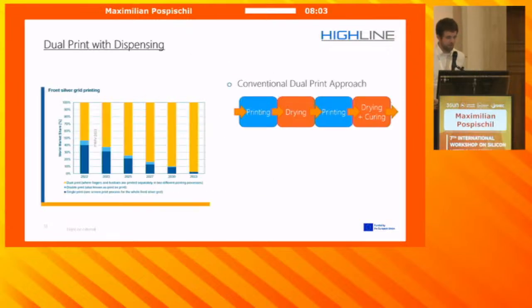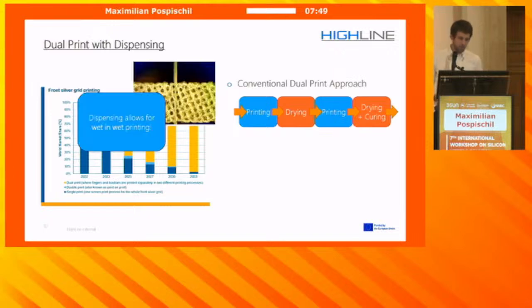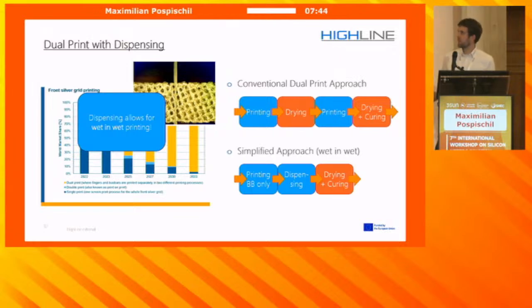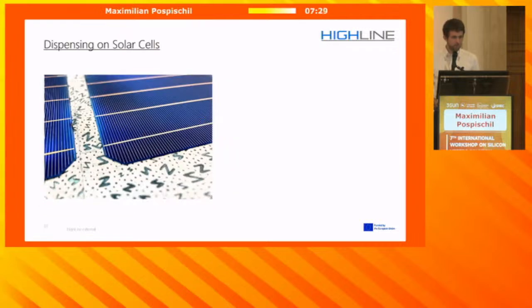So first thing, when you apply bus bars and fingers and you want to have different paste optimized for different situations, usually you do a dual print, and dual print in screen printing means there's a drying step in between. We are contactless, so we can, of course, do wet-on-wet printing, and that means you save one drying step. This makes your factory shorter, and your wallet stays a little bit more filled when you invest in new technologies there.